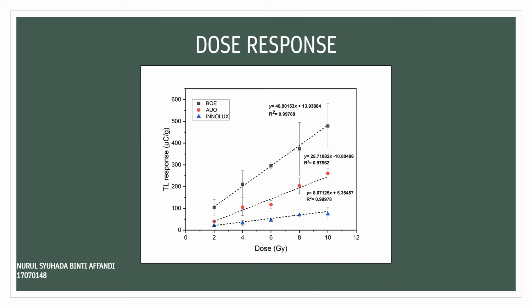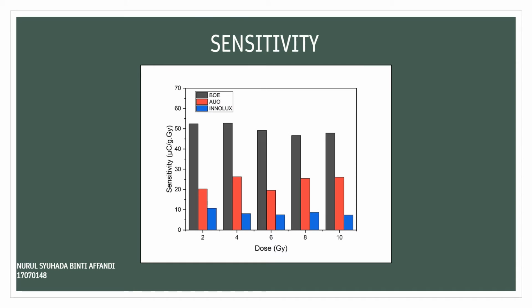Why is the linearity criterion important? This is because efficient and dependable thermoluminescent dosimeters should result in a linear relationship across a wide range of doses. We can see that BOE is the highest among the 3 types of samples. The second is sensitivity. From this, we can conclude that BOE has the greater sensitivity over all dose ranges in comparison to the other 2 types of sample.